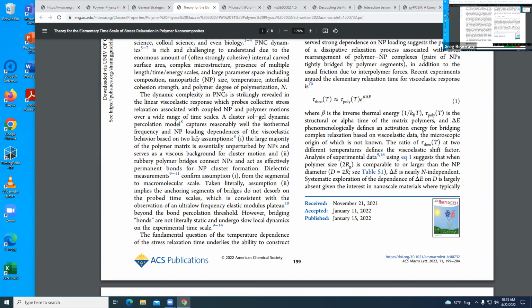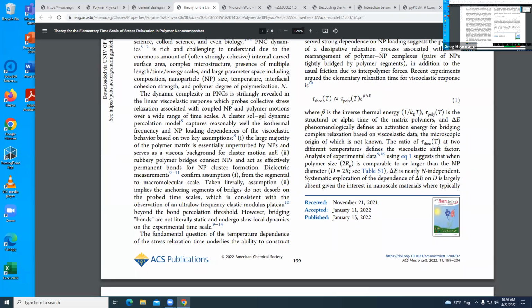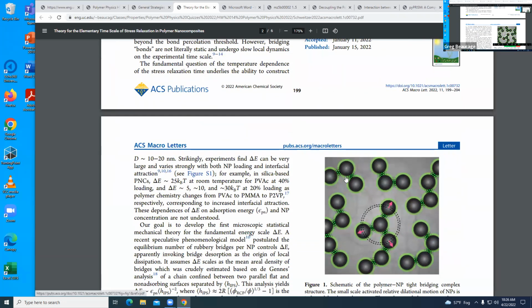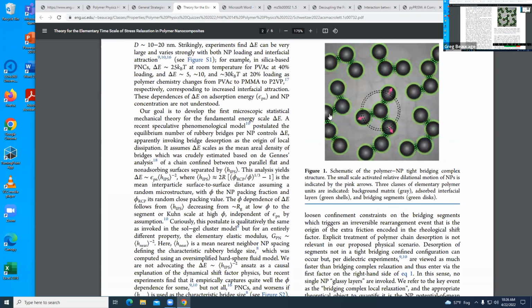So he's going to take the X-ray data, do PRISM to get the correlation function, use the correlation function to get delta E, and to get this N_B, which is going to be how many of these monomer beads are between an average particle. And then because that all works, and this model is consistent with the data, he has a model for what's happening with the nanoparticles. So there are a couple of problems with that whole picture.